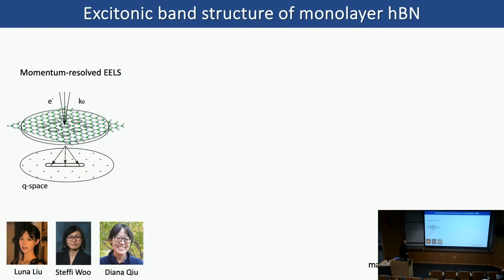We want to answer the question whether monolayer hBN has a direct bandgap or an indirect bandgap. The technique we use is also inside an STEM. It's called momentum resolved EELS, where when the beam goes across the sample, you spread it out. So there's a diffraction plane here, which marks the q space. It's actually the momentum space. And then we further spread them out in the energy space. So you spread them twice. One degree of freedom is the momentum, and then the energy, from which you could plot a band structure. This is the momentum resolved EELS.